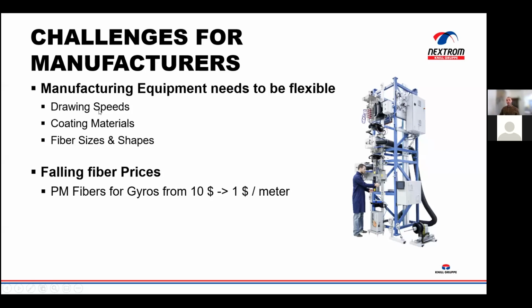Then other factors may affect the drawing speeds. The coating materials vary. The thermally cured materials, for example, tend to be below 25 meters per minute, whereas for acrylic, there are specialty fiber manufacturers probably running in the 500 meter per minute range. That's going to be on the upper end. For a telecom manufacturer, our current telecom tower is approximately 3,000 meters per minute. So there is a lot of room for growth in drawing speed if it's needed, and I'll talk about that a little bit later.